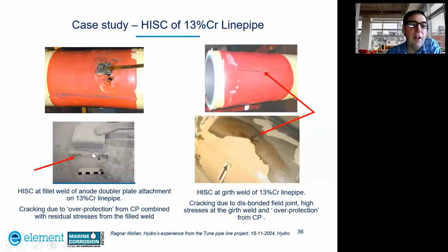So this crack was located at the fillet weld of an anode doubler plate attachment on the 13 chrome line pipe. And the cracking was due to overprotection from the CP system combined with residual stresses from the fillet weld.